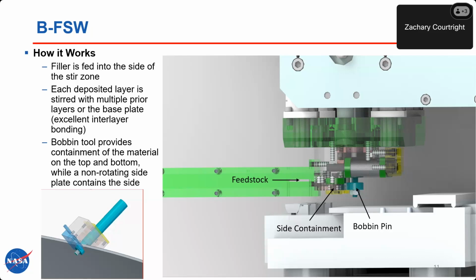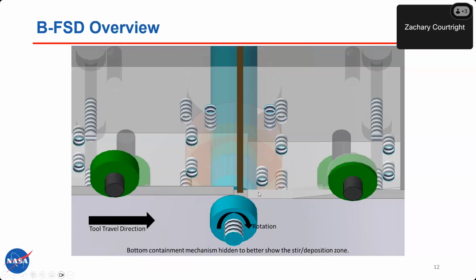Next slide, please. Okay, so this helps to elucidate it a little bit more. That brown piece would be a filler material rod coming in through any number of different feed mechanism styles, but this was a ram rod. And then basically the pin tool, the plate, or it could be a dome or a cylinder or a number of different shapes, the tool rides along the side of that. For the initial start, you may start off with a notch to make it easier to contain the initial material. But depending on how much you're depositing with each pass, that may not actually be necessary.